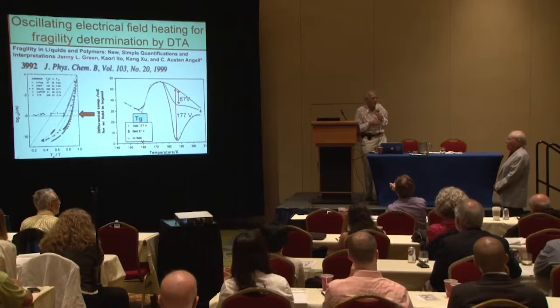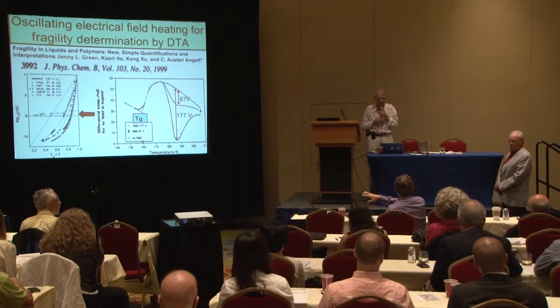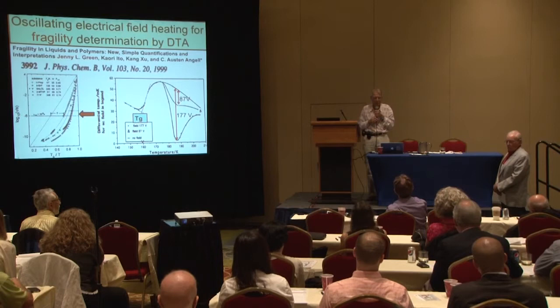Yeah, I was just commenting about glycerol and PG. I think you're talking about pure substances today. And if you mix them with water, to produce a reasonable concentration for cryobiology, then they're much more fragile. That's probably true. Although if I look at lithium chloride water near the glass transition temperature, doing some suitable measurement, I go from the very easily glass-forming, crystal-like, I should say hydrate-like, composition, and adding more water, it becomes stronger. It becomes stronger because we're building up the water hydrogen bond. I don't know why it is, but they definitely become stronger. So I don't know.